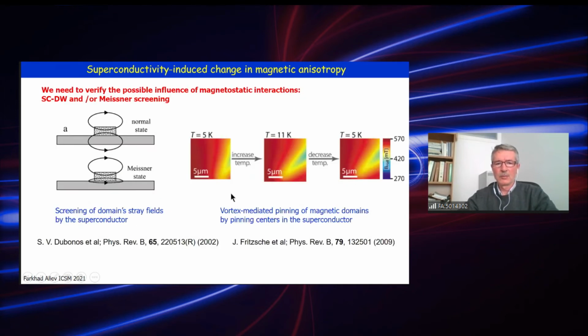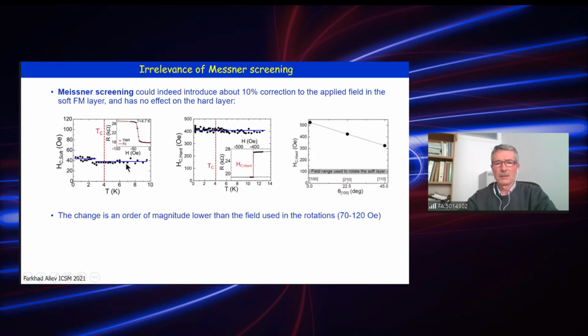Also, we analyzed the possible effect of Meissner screening and interaction with domain walls, which was previously reported. Here you see the possible effect of Meissner screening: the change of soft layer coercive field is only below 10%, which is quite small and does not affect our effect. Hard layer switching field doesn't change at all.